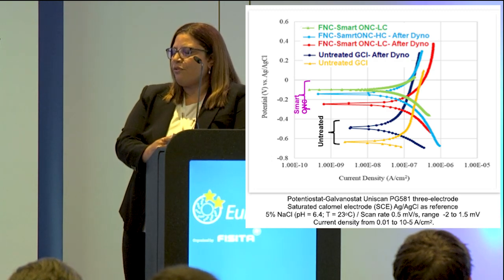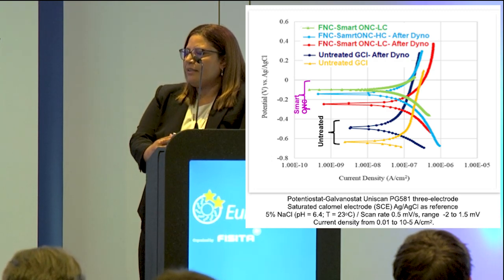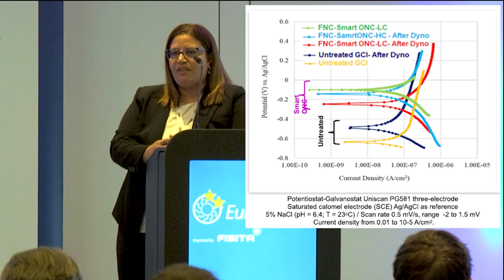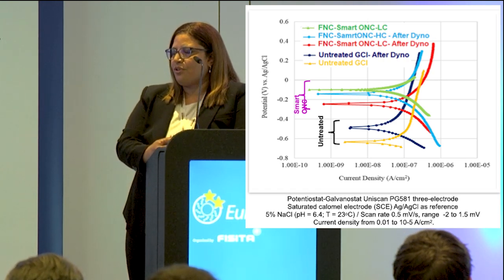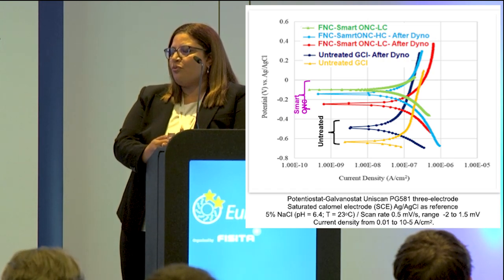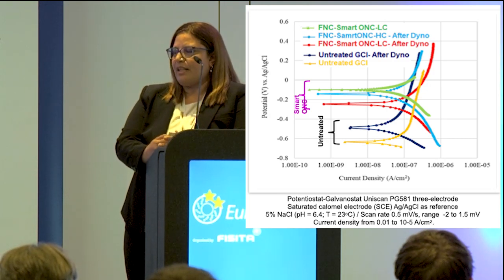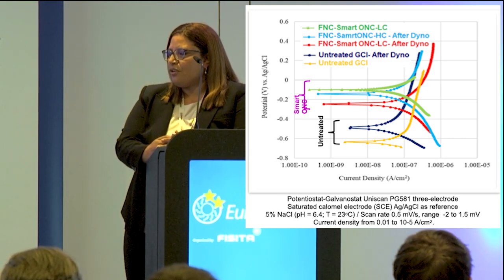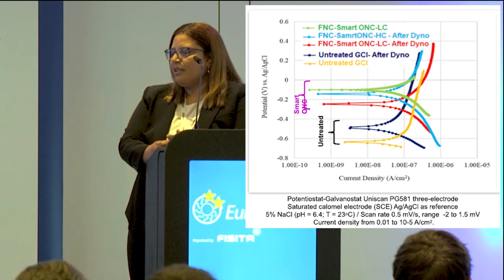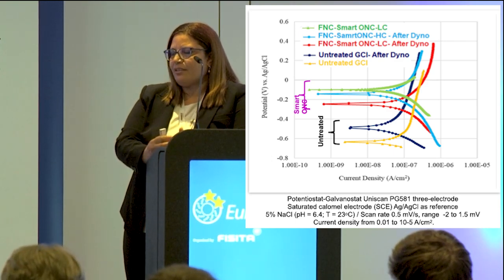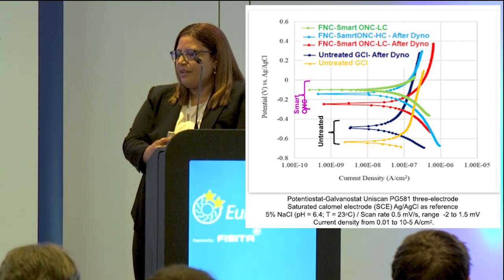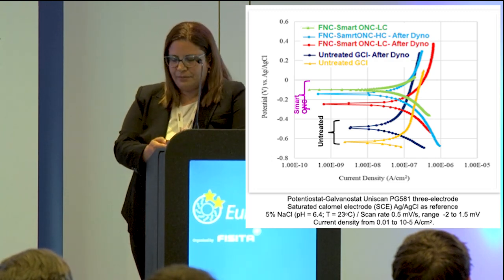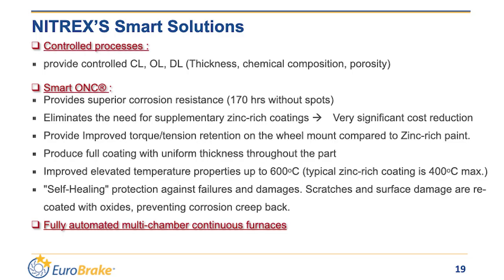The low carbon variant, the green one, shows the highest corrosion resistance, which decreased after dyno testing because of material loss from Smart ONC. And the high carbon variant shows higher corrosion resistance compared to the low carbon variant after dyno testing because of the thin top layer that formed from the pad material on the friction surfaces, which acts as a protective layer.